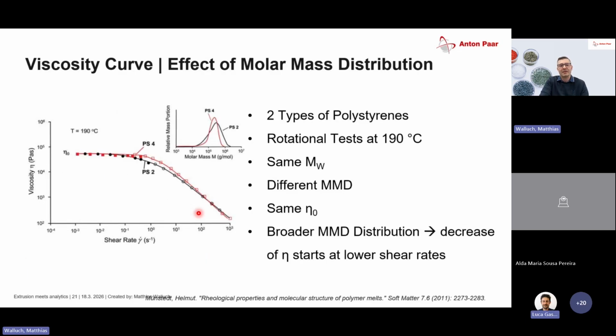And if we have a material with a different distribution, so they have the same average molecular mass but a different distribution, we see the plateau is the same, the high shear rates are basically the same, but here in the middle, something changes. If we have a more narrow distribution, this area is at a higher level than with a broader one. So we can directly see, if we compare the same materials, the impact of different distributions and different molecular masses.